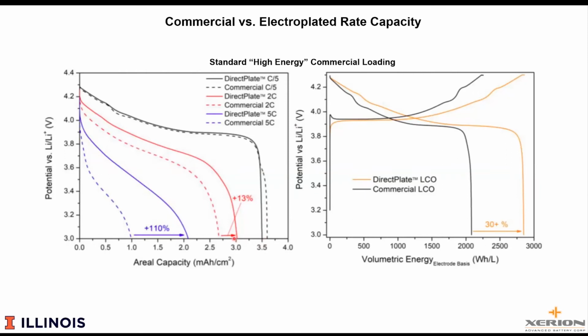Now a 30-minute discharge, here's the difference in the energy between commercial and the plated. And then in a 12-minute discharge, the commercial electrode only retains about 25 to 30% of its original capacity, whereas by creating these low tortuosity structures, one retains on the order of half. The loading is also higher, so one of the reasons this works is because it can be thinner at the same capacity. And so a plated electrode of a given thickness has 30% more energy than a conventional slurry electrode.